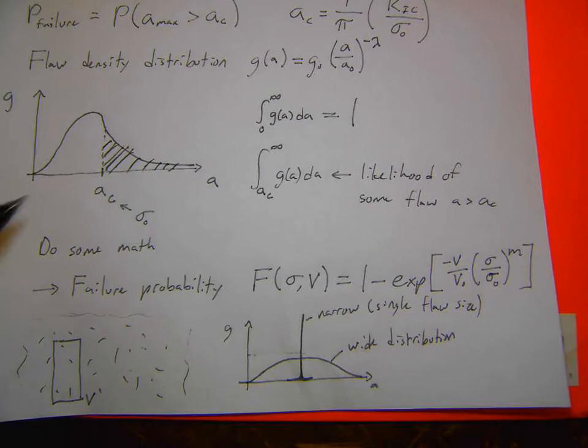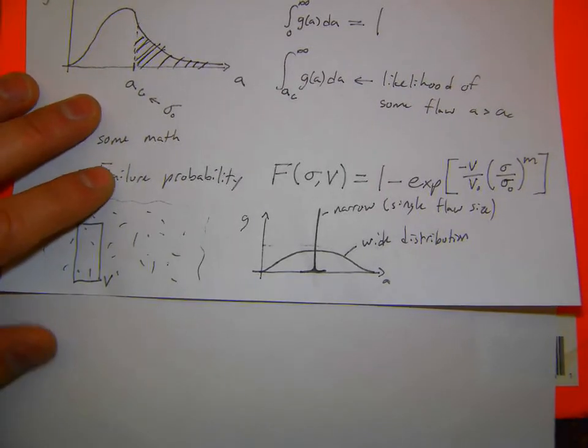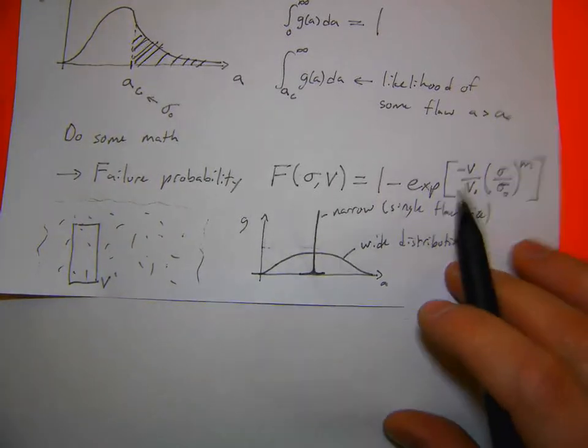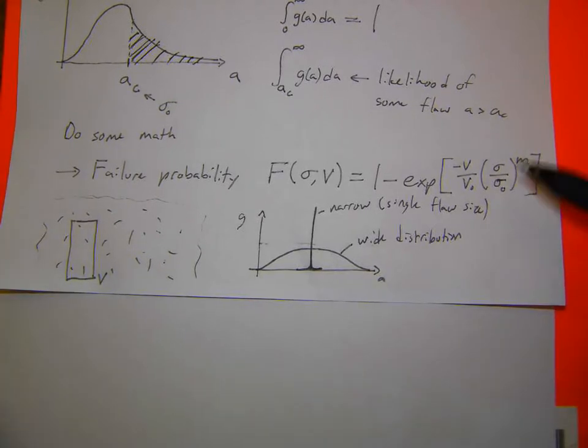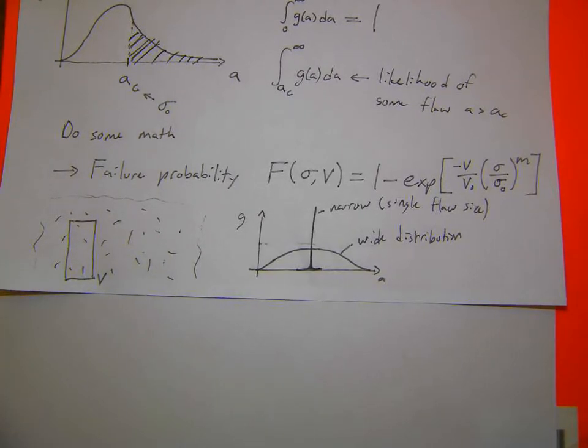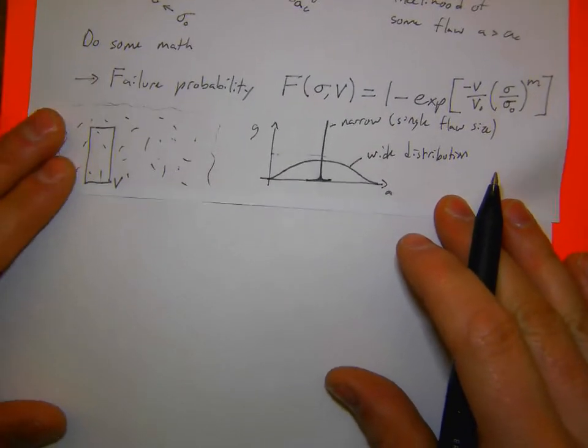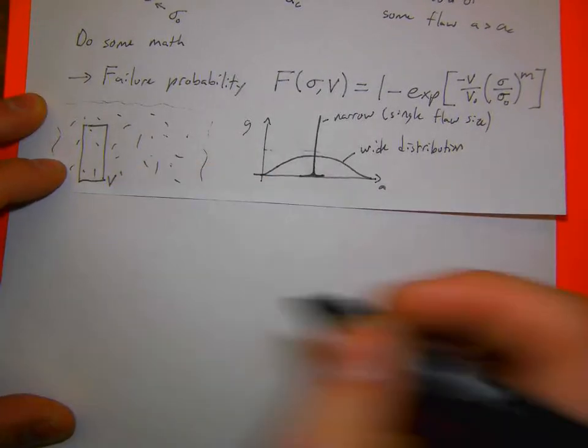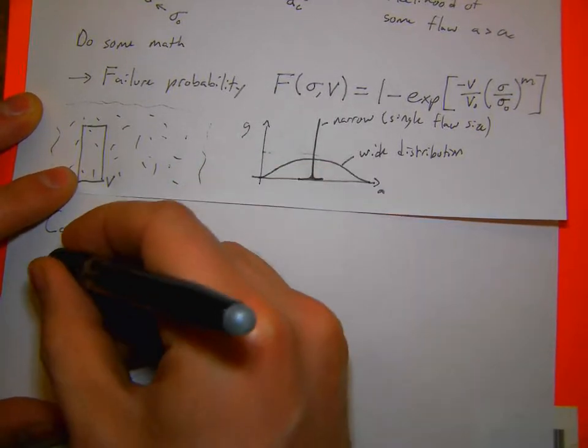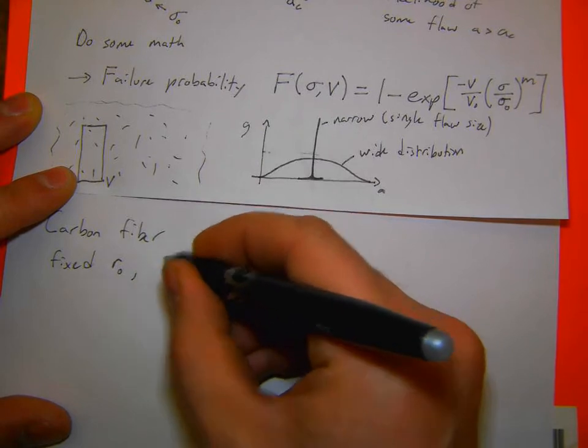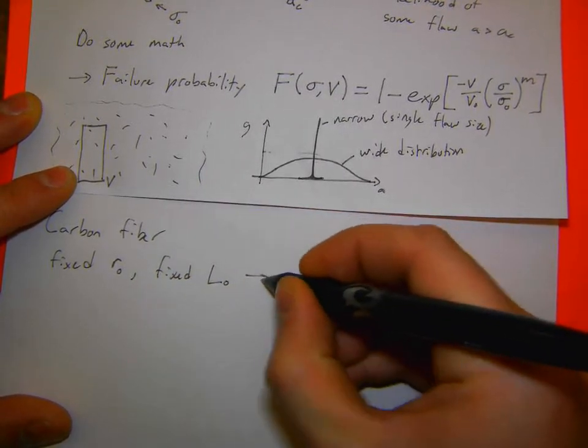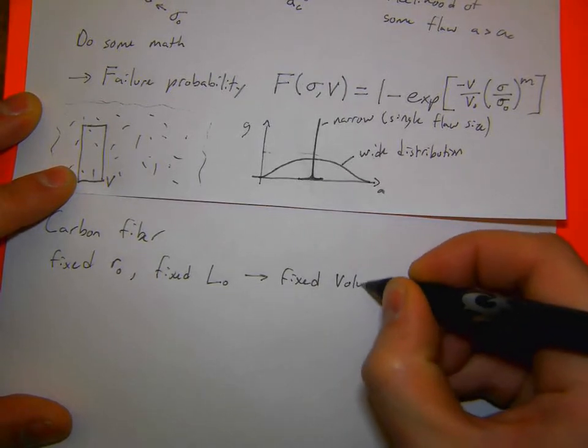So what we can do with this now is perform some experiments to see when and where failure will occur. In practice, I take a fixed part of a fixed size and test that part over and over again. It's common with something like carbon fiber. So let's say I'm going to take some carbon fibers. They all have approximately the same diameter or radius, and I'm going to choose some fixed length. So then I have some fixed volume, V naught.